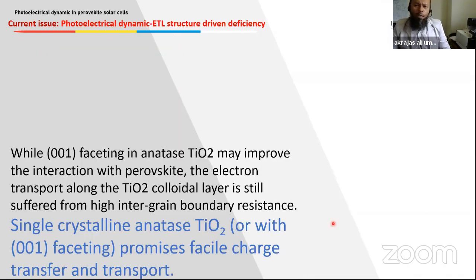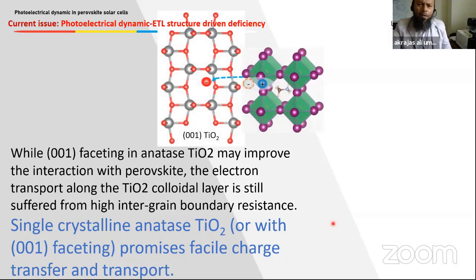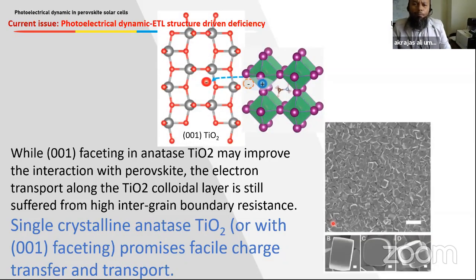But while the 001 facet may improve the coupling, when we use this kind of structure as ETL, as we can imagine, it will also have large interfacial grain boundary resistance, so we may again lose precious photocurrent during the transport. So we need to find a way to solve the problem.